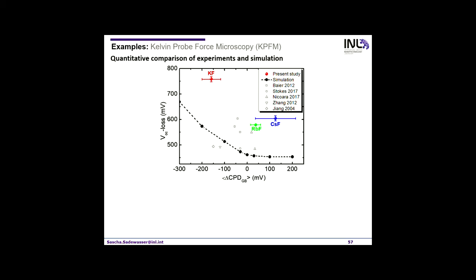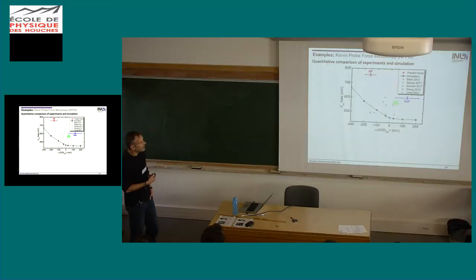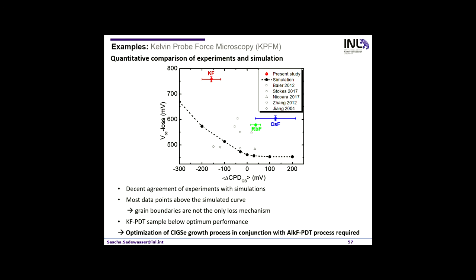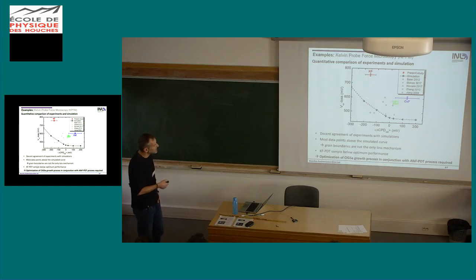And then we can look in the literature and find, in some cases, studies with KPFM that looked at these changes here. But in many cases, you don't find a corresponding device. So there are only a couple of papers where device efficiencies were actually reported, and they also come to lie more or less on this line. So there's a fairly decent agreement between the experimental results and this behavior in general. But of course, all of the data points are above this line because there are other loss mechanisms, of course, interfaces and so on.